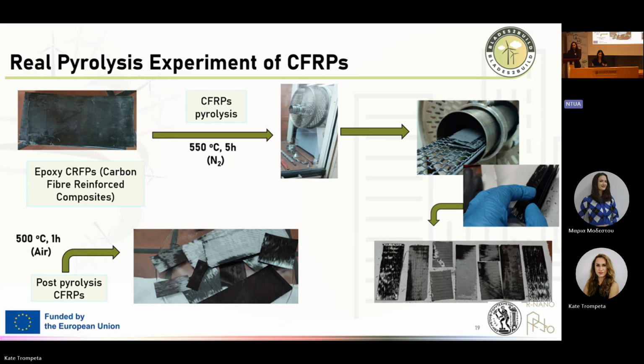This is the protocol that has been developed by our colleagues in the lab, specifically Stefania Termine, where the epoxy CFRPs are first treated in nitrogen atmosphere at 550 degrees for 5 hours. This is in a lab scale apparatus. And then a post-pyrolysis treatment for 1 hour at 500 degrees in air. By this, as you may see, we are able to separate the layers of composite, the different patches that constitute the CFRP specimen, and they are really glossy and clean, as you may see from the pictures, which means that we have a very nice recovery of fibers without destroying them.